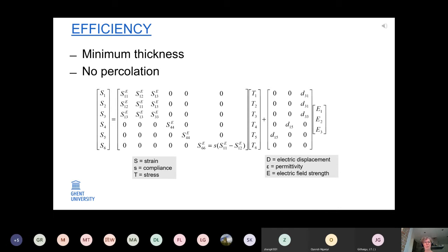That's why we need a minimum thickness, but the minimum should not be too low, because then we may have percolation of current between the two electrodes, and then you get holes and the system is broken, it doesn't work anymore. Particularly during the poling, where we need a high electrical field, this is an issue.